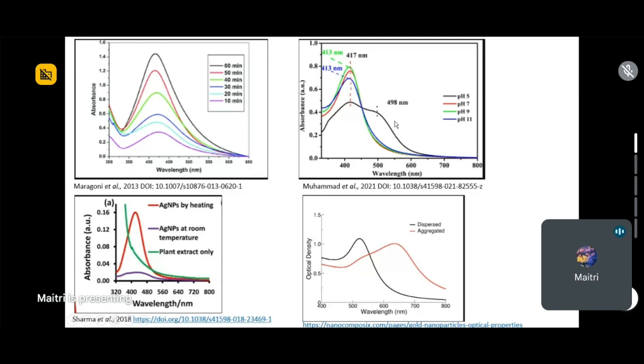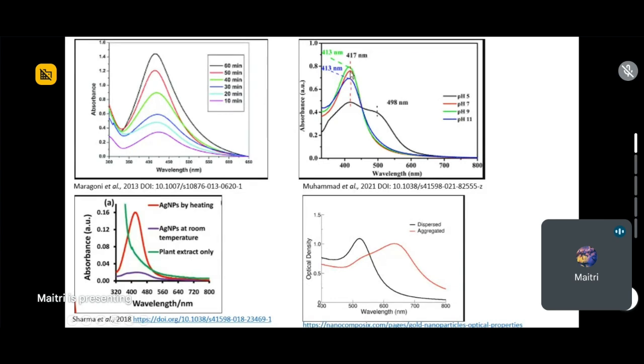of AGNPs has reduced, and this thing, the formation of a second peak over here from 420 to around 498, this is called a red shift. A red shift means aggregation of AGNPs, and this helps you understand which pH is useful for the formation of silver nanoparticles. So, like this figure is clearly telling me that pH 5 is just not to be considered. If you wish to consider, we should consider 7 or 9, not even 11, because 11 is again reducing my yield.